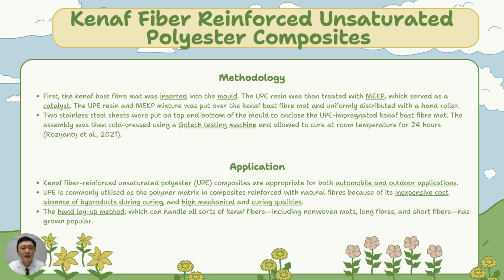So next we will talk about the kenaf fiber reinforced unsaturated polyester composite. First, the kenaf fiber was inserted in the mold and then treated with MEKP, which acts as a catalyst. Then stainless steel sheets were put on the top and the bottom of the mold to enclose the UPE impregnated kenaf fiber mat. And then we do a cold press using a testing machine and let it cure for 1 day at room temperature.